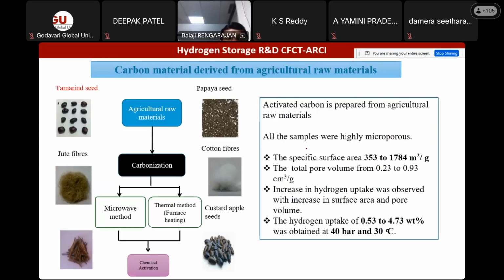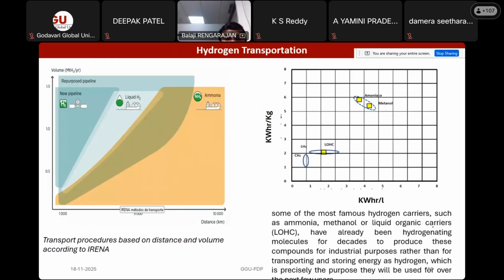That is the target of DOE, the Department of Energy, USA. If you have a porous material which can accommodate 6 weight percent of hydrogen, then it is a success. In this context, we were able to accommodate up to 4.7% in the carbon-based material derived from this kind of seeds. But the uniqueness is that you apply only 40 bar pressure at room temperature, because some materials require high pressure and elevated temperature. That is not the case for us. So this material can be handled at 40 bar at 30 degrees Celsius with a hydrogen uptake capacity of 4.73 weight percent. But there is a way to go to reach 6 weight percent. That work is going on right now.